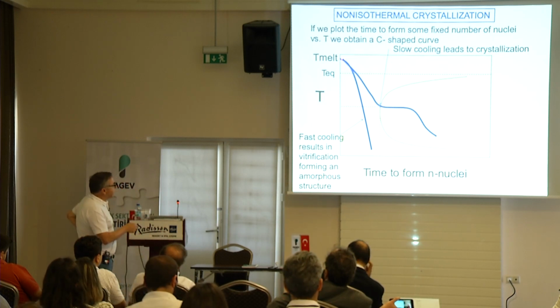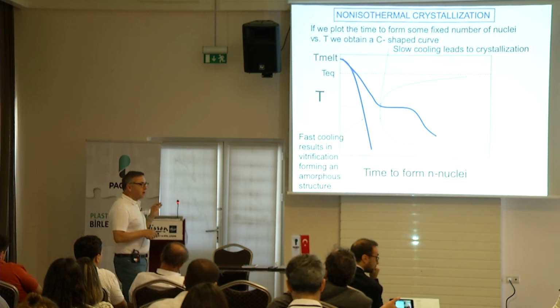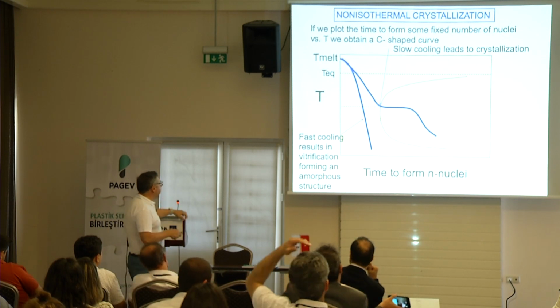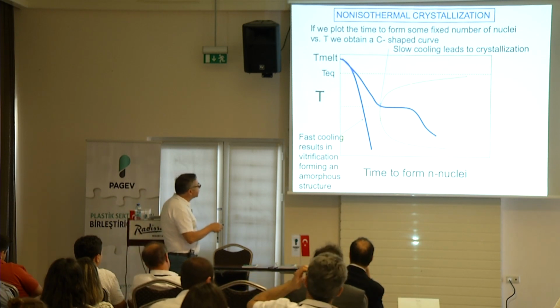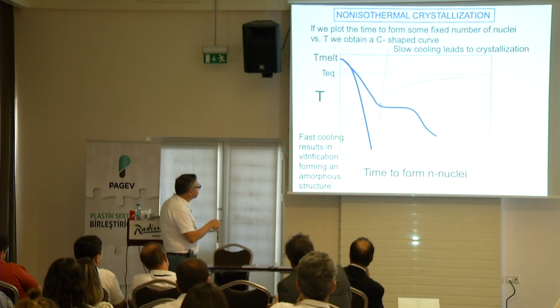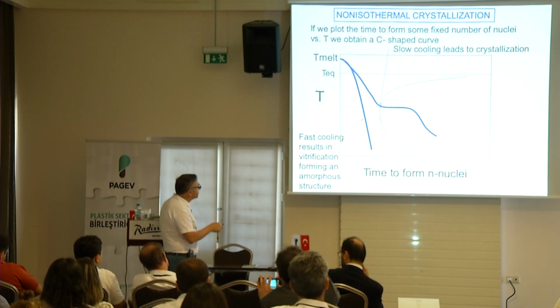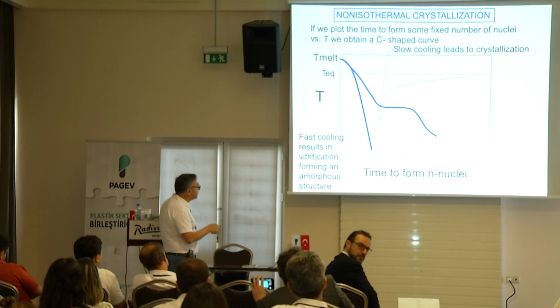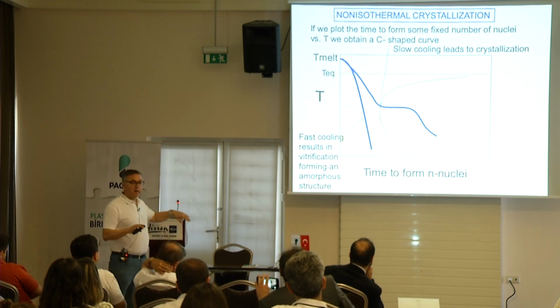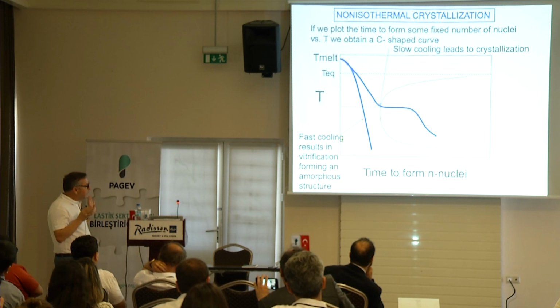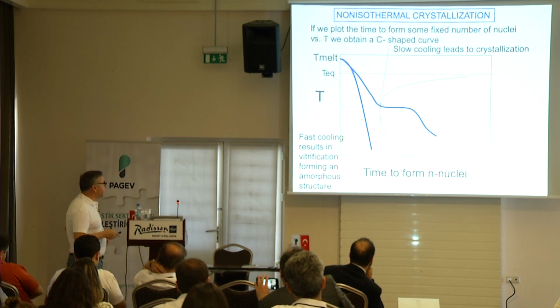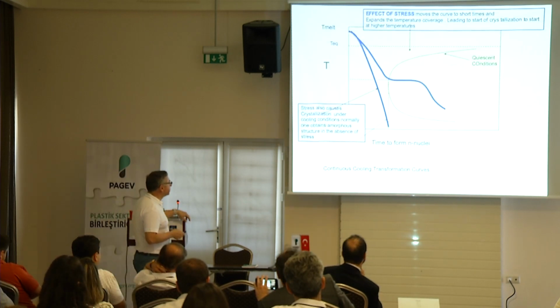So if you do a slower cooling, the nice thing about these kinds of diagrams is that it will tell you at what temperature it's going to start crystallizing. If I do a slower cooling, it's going to crystallize at higher temperatures. If I have a faster cooling, it's going to crystallize at lower temperatures. If I go even faster, it will bypass this, and it will never crystallize. This is the portrait. This is the important understanding of non-isothermal crystallization.